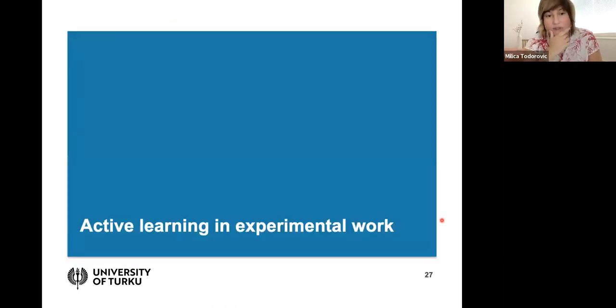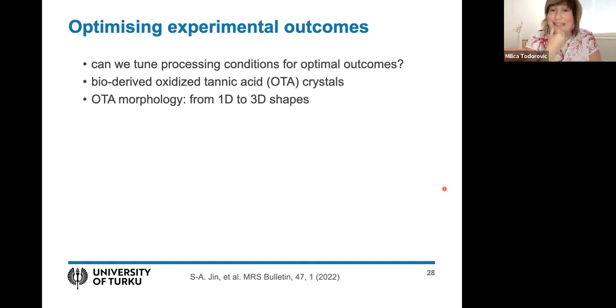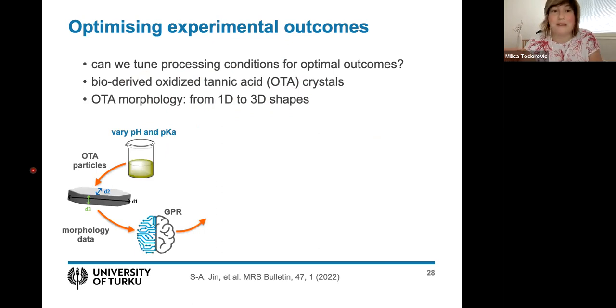Okay, I want to quickly go on and mention some applications of active learning in experimental work. Basically, we realized that this is a powerful optimizer, and you can optimize structures and optimize properties. So then we wanted to learn if we could optimize experimental outcomes. And what we started with is experiments on tannic acid nanoparticles, which are bio-derived. And we wanted to adjust the processing conditions so we can preferentially create 1D particles or 3D particles. So that was the task from our experimental colleagues.